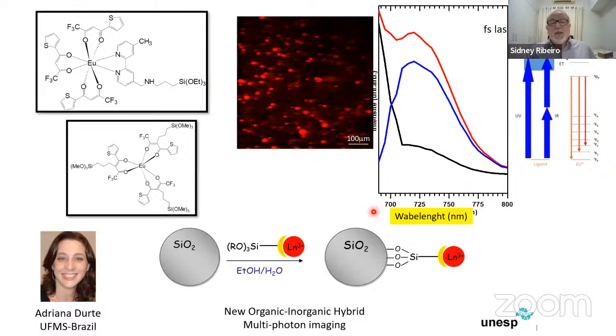We can use the silica particles and modify them. In this case, with these complexes, you see here europium, and these are the organic ligands around europium. One of these ligands is modified with an alkoxide, a silicon alkoxide group. This will allow us to graft these luminescent species on silica particles. So we did this, and these silica particles modified with the luminescent complex can be used in imaging. You see here an image of a microscopic sample excited in the infrared. So what we have here is multiphoton imaging.